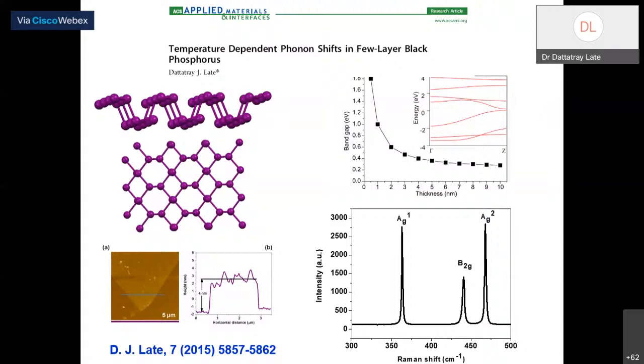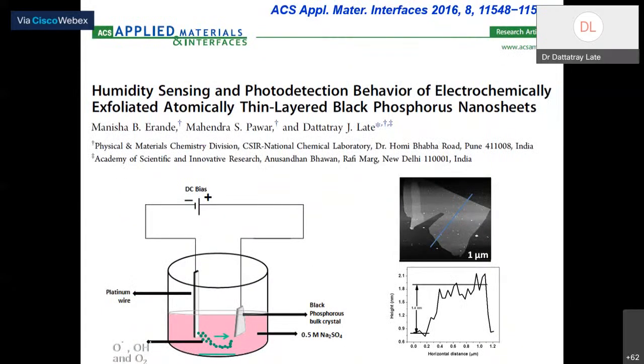Even we have done the various layers also we have fabricated, and then the thickness tuning, band gap tuning as a function of thickness also done, and we have used it for the kind of application. For example, the synthesis was done by a very simple electrochemical exfoliation method, where you need bulk crystal, and platinum as another electrode.